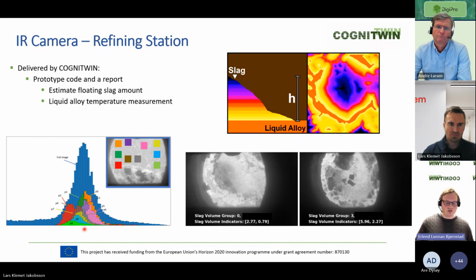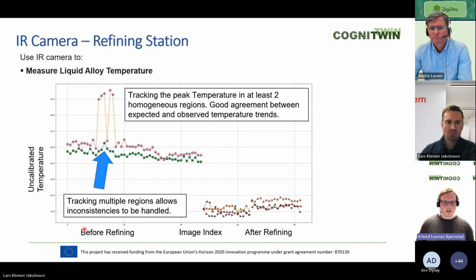So we had to find a way to deal with this, and this has to do with dusting and waves. You get these small slag floats that come up and that sort of thing. Lars, next slide. But if we are able to isolate different areas with the temperature, we get these different lines where you can see that we have this consistency, which allows this inconsistency to be handled while you get quite consistent behaviors over time.